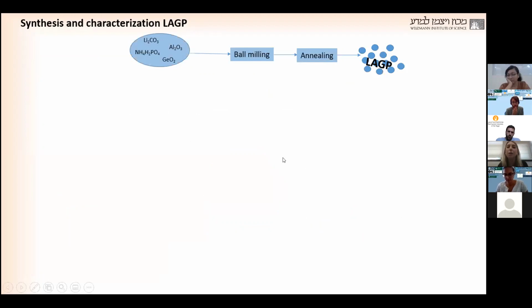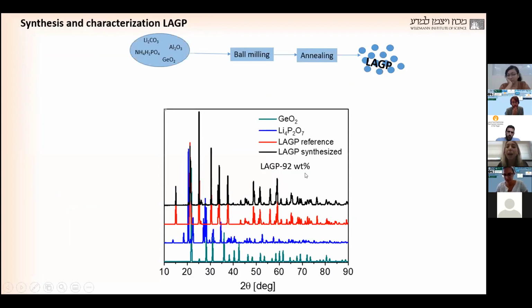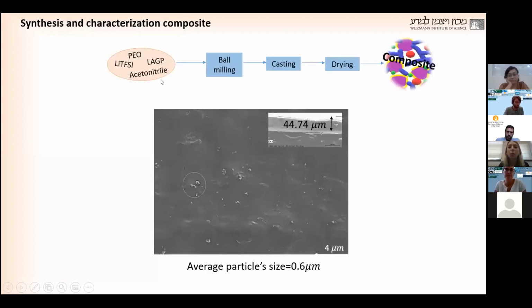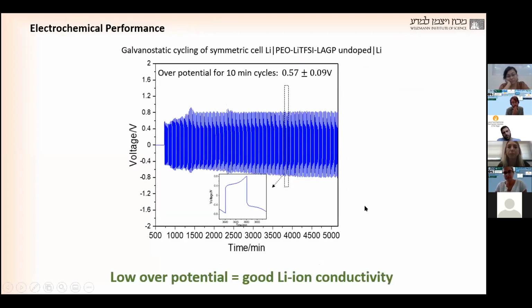So we synthesized the LAGP and characterized it, and we can see that we have high weight percent. Also, when we put dopants inside of the LAGP, we still get a high weight percent. In addition, we also synthesized the composite, and we checked it in the SEM, and we can see here the spread of the particles of LAGP, the white particles, that it's really homogeneously inside of the composite. Also really important to understand what is the lithium ion conductivity of this composite.